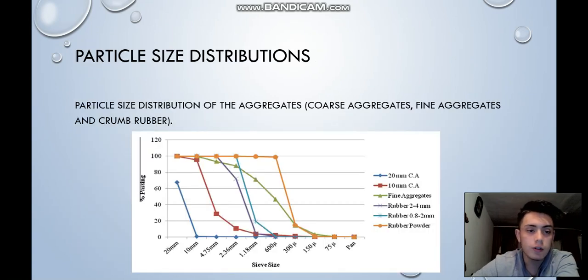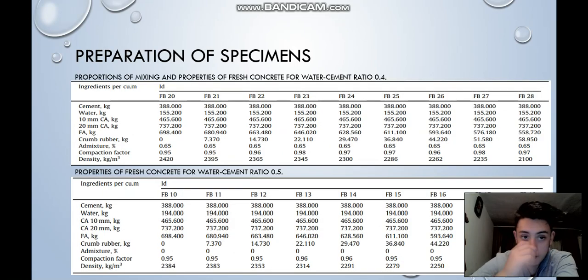Particle size distribution. Particle size distribution of the coarse aggregates, fine aggregates, and crumb rubber. You can see in the figure the percentage on the size. You can see that the rubber powder goes to the first levels, being the finest material compared to the aggregates of 10 and 20 mm. Preparation of specimens. In this table you can see the fresh concrete properties for the water cement ratios of 0.4 and 0.5 respectively.